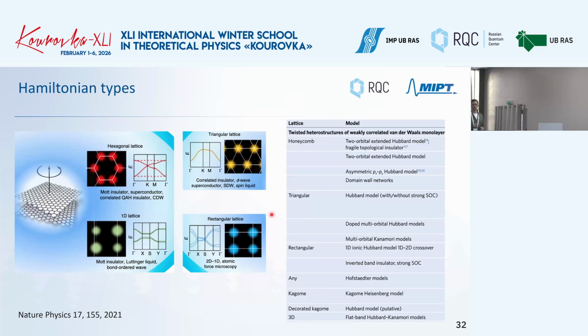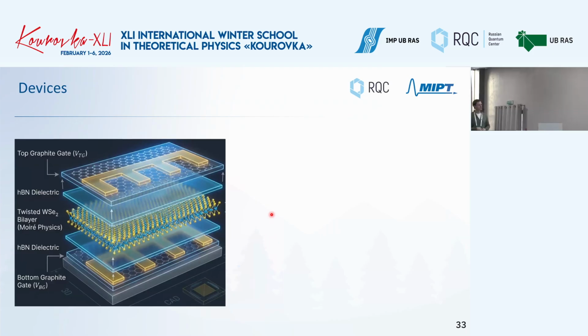In order to cruise along these different Hamiltonians, as I mentioned, you can make the gating, but in real time, this gating should be done in a more sophisticated way. So you must have basically two gates, a top gate and a bottom gate. This is the representation of how the device would look. You have your moiré structure in the middle, and then you have the electrodes on top and below, and you have the top gate and the bottom gate.